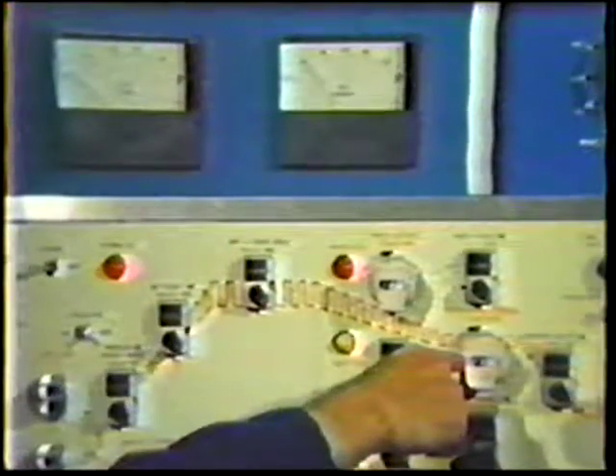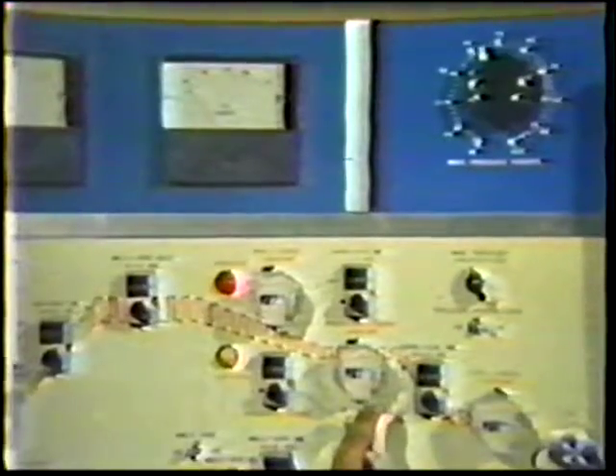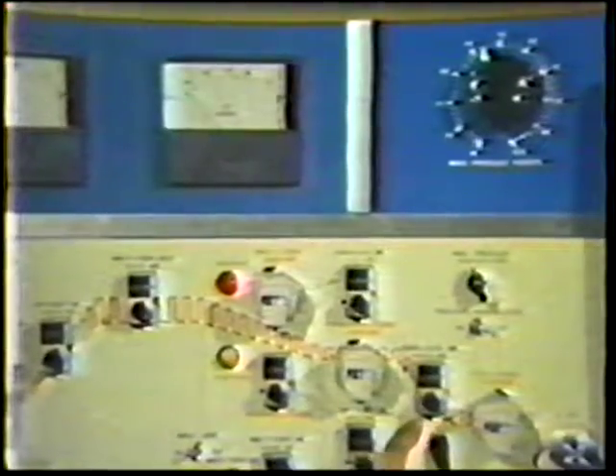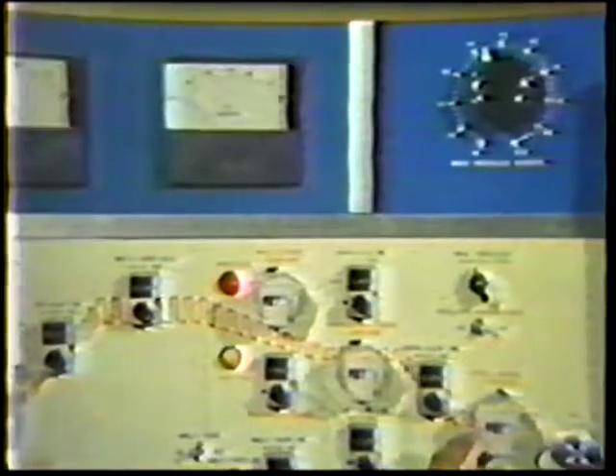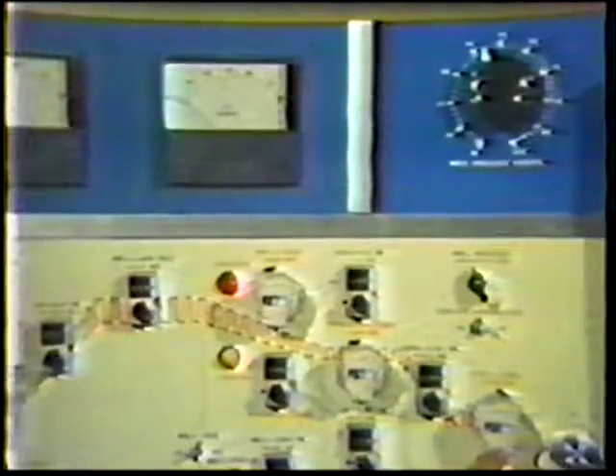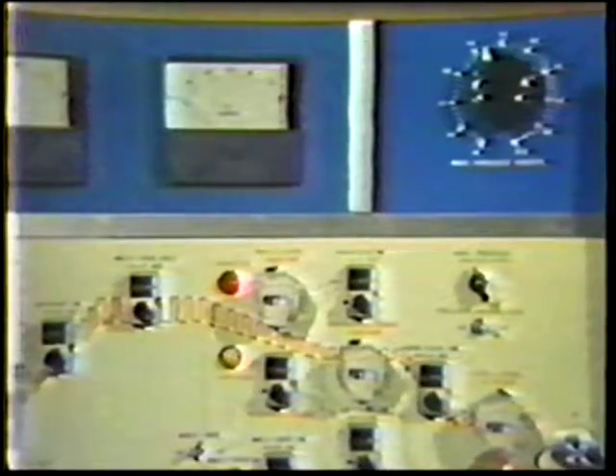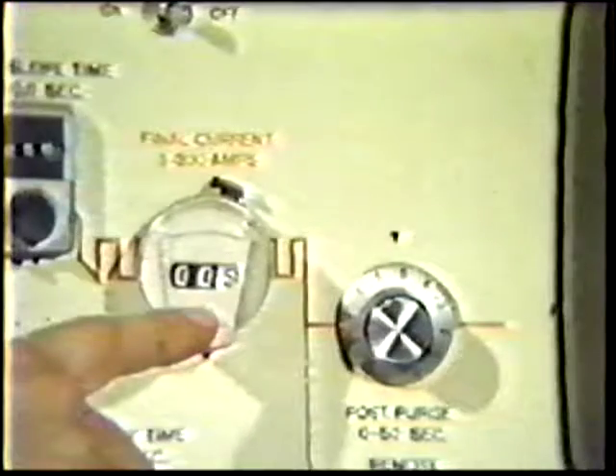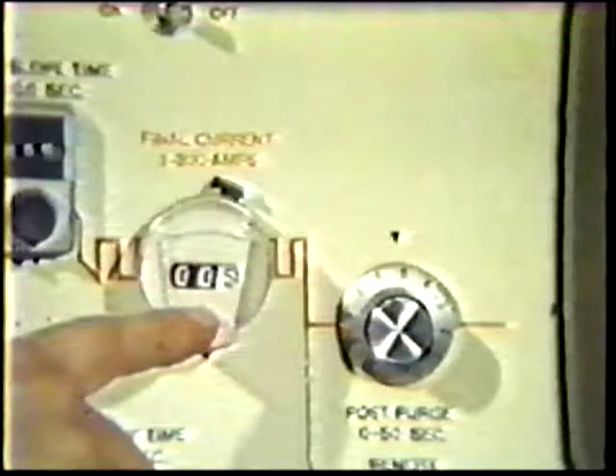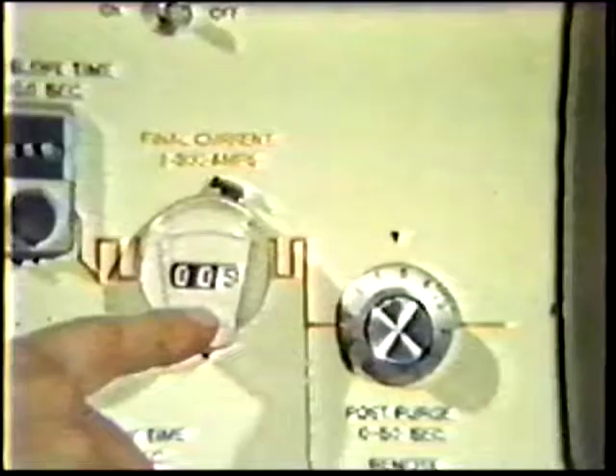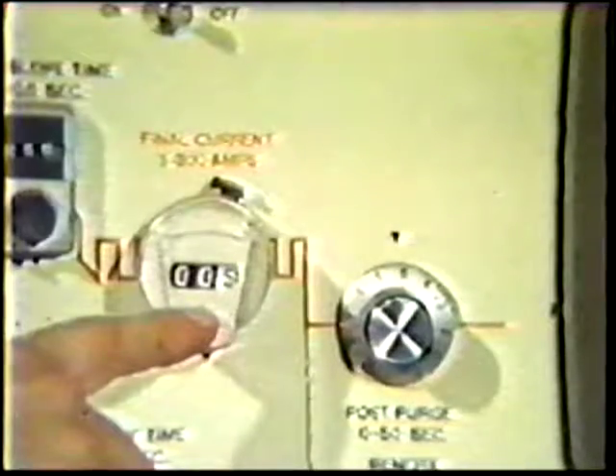Once the weld has been completed, downslope begins. Downslope gradually decreases the current from the tapered current value to the final current. This method produces the same result as cratering out with the manual method. This reduces the possibility of crater cracks. The current is normally allowed to flow for a short time at final current to allow post-heating to take place.